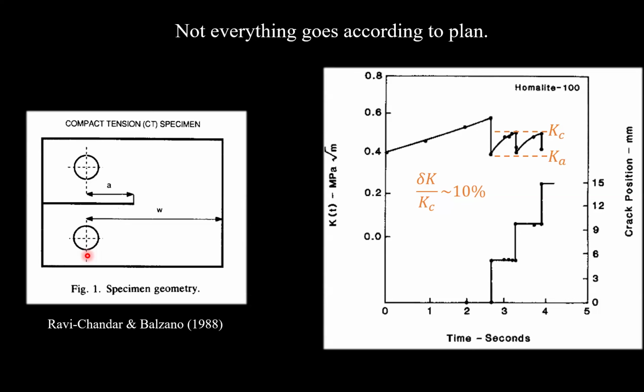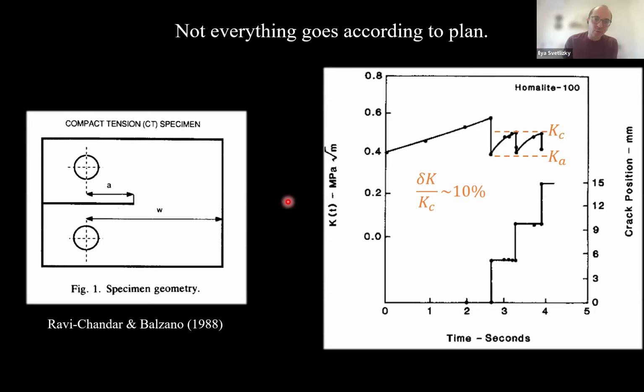So the sharpness of the crack tip is why you're seeing exactly the same thing in both of these, and if it's more or less the same material. Your sharpness jumps, of the crack tip, yeah? Yeah, your crack jumps, it has a very sharp crack tip, and now you're reloading it. And you're giving it time to creep a little bit, so the process is changing.